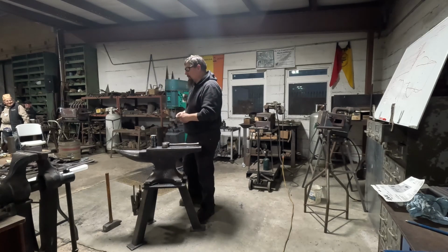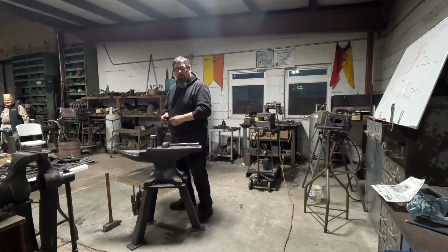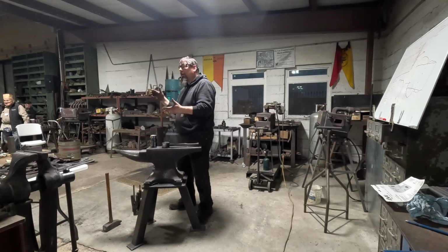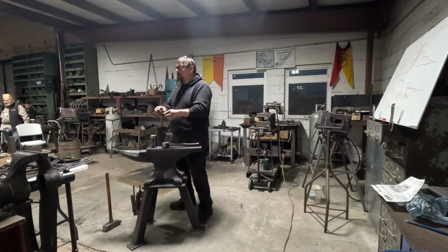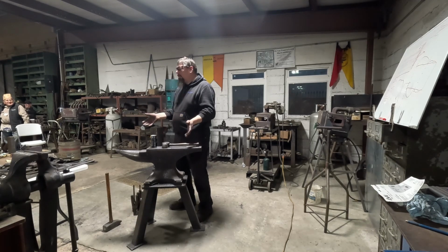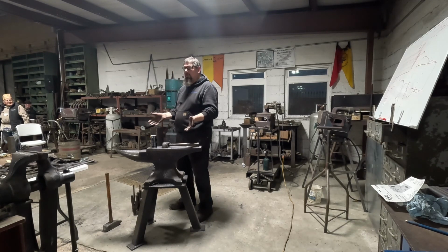One of them is the one I'm passing around. Cracks everywhere. What is that? This is not supposed to happen. It's not wrought iron. All right, well, is it maybe a super high carbon steel? Did I get it too hot for the composition? Not knowing, we do a spark check on it, and it doesn't spark like high carbon steel. I don't know if we did this, but we could have heated it up and quenched it in water. Does it get hard? No, it doesn't. Oh my God, this is completely mystery material to me.